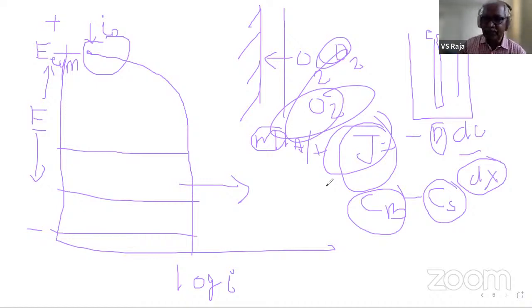So the limiting current density is a condition where the surface concentration of the species to be reduced or oxidized, either way, becomes zero. Now, mostly we talk about the cathodic. Why? Because cathodic means these ions are coming from a solution. Anodic, we don't talk. Why? At least anodic for metals, we don't talk. Because the metal surface is rich in metal ions, right? So always there is an infinite amount of metal on the surface. And so you don't get diffusion control for the anodic reaction, especially when dealing with metal corrosion.